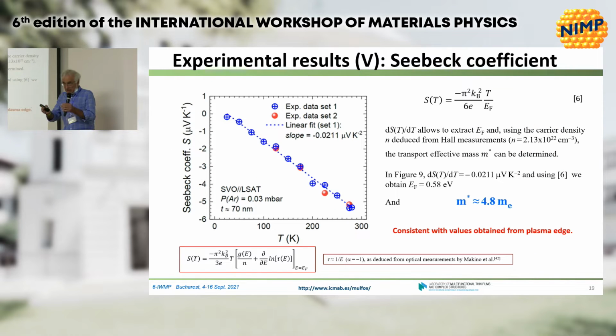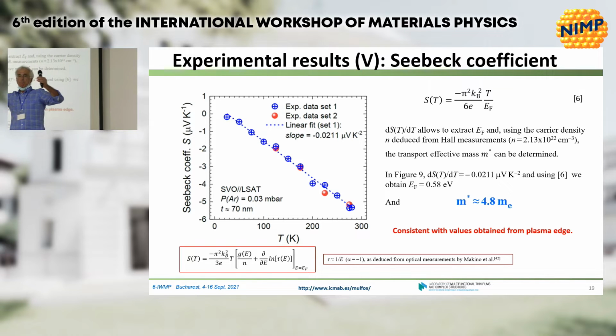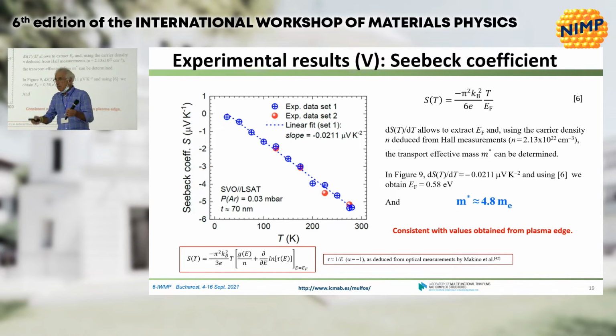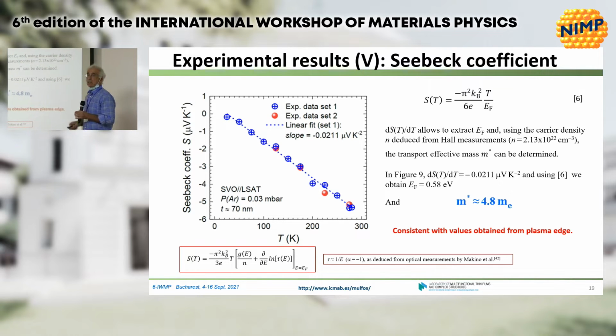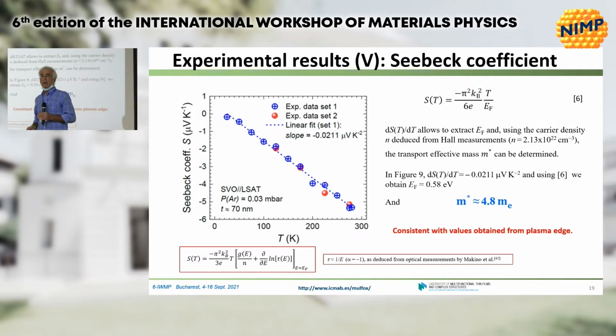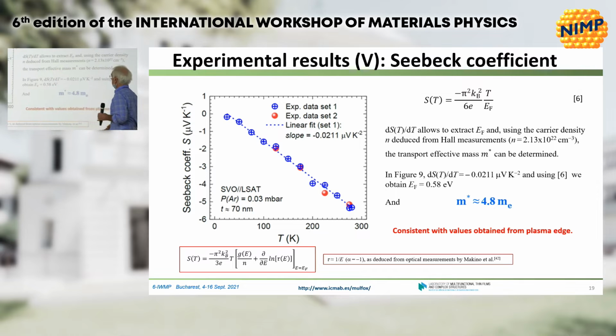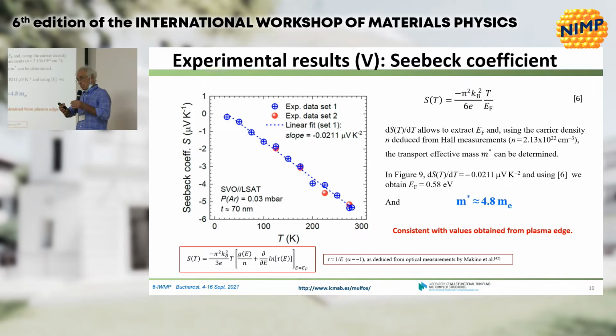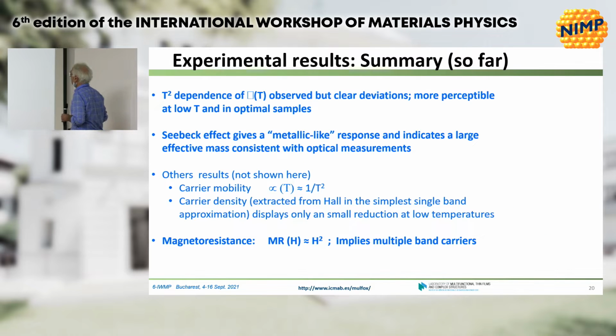We measure the effective mass of the carriers, not only from the plasma frequency, but also using the Seebeck effect. Here you see the data from the Seebeck effect. This is the Seebeck effect as a function of temperature, a beautiful straight line as expected for a metal. From the slope you determine the mass, and it's roughly 5. So these are really heavy electrons. So the data fits with the idea that the electrons are heavy, but does not fit with the idea of strongly correlated electrons in the metal.